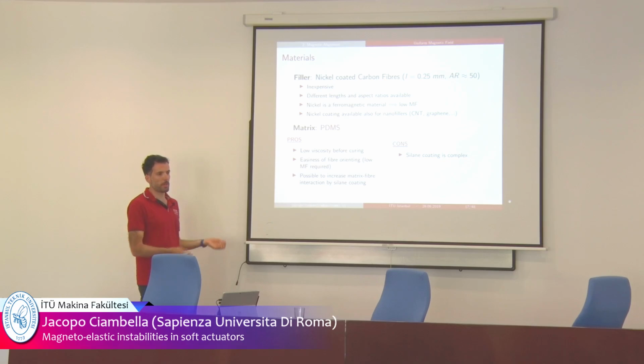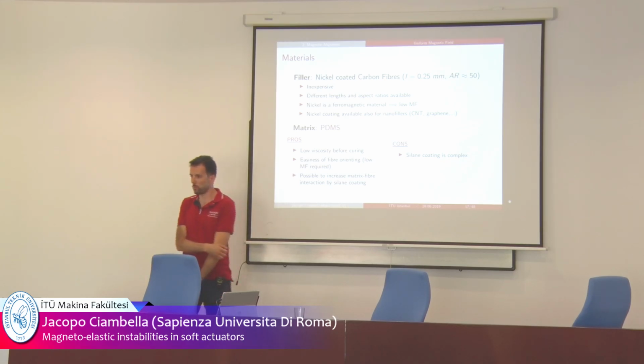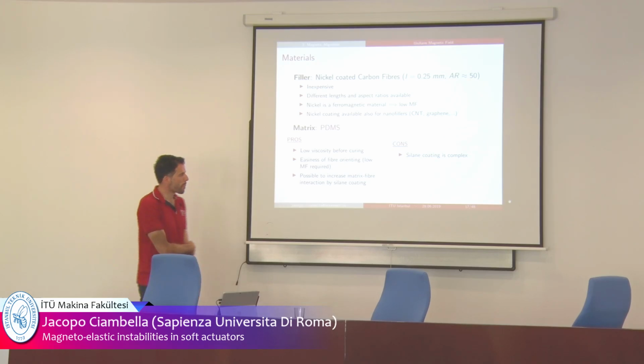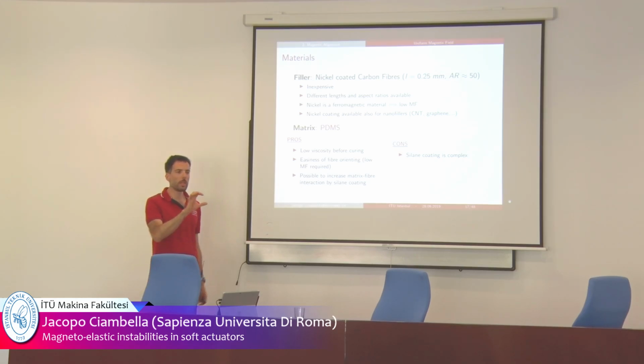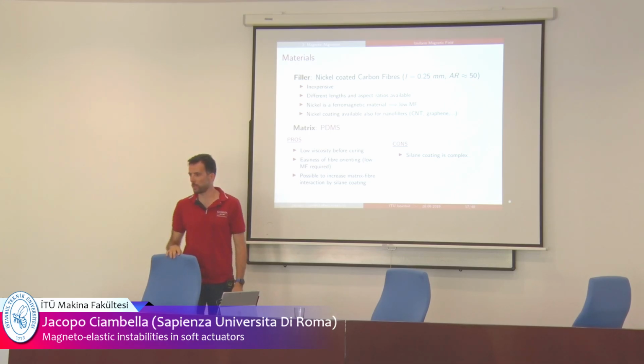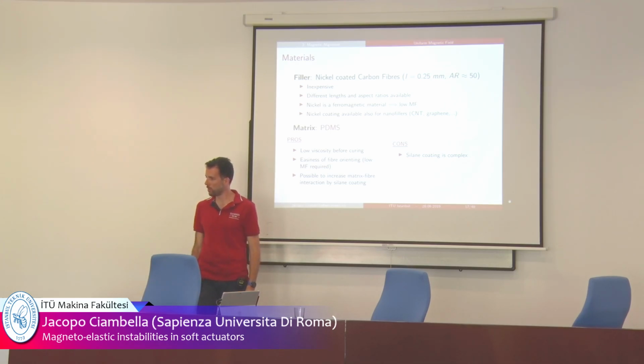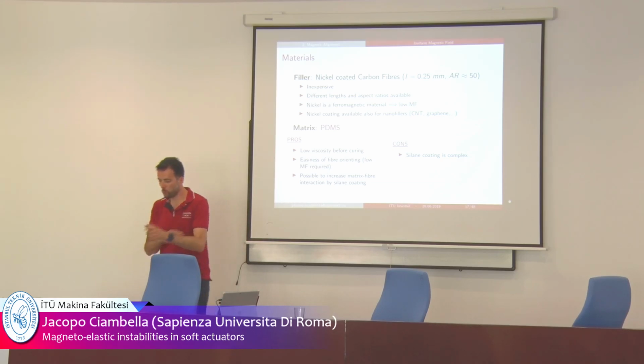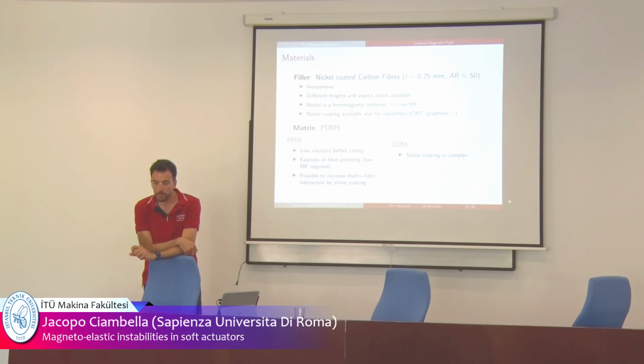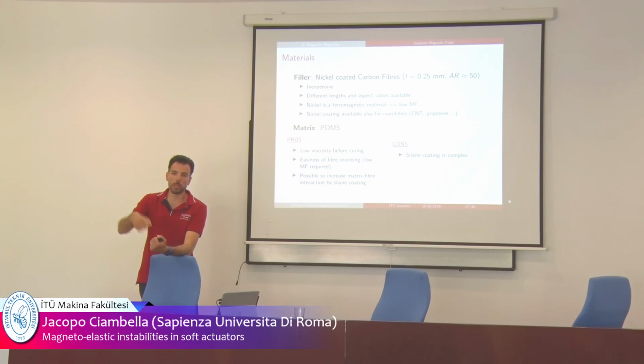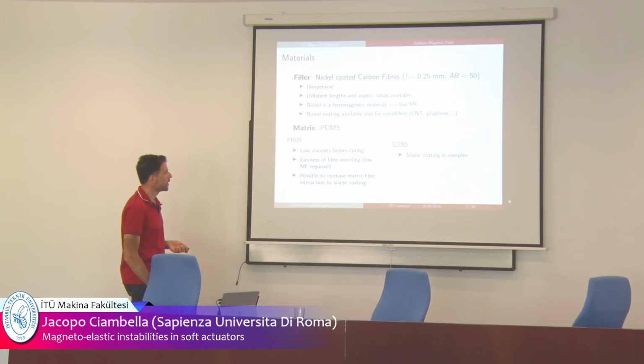PDMS is extremely easy to find, it's inexpensive, so it was the first elastomer we tested. The problem with PDMS, as I showed you, is that it is not easy to attach anything to PDMS, so it is very difficult to get a very good interaction between the matrix and the fiber. In fact, as we have seen in our experiment, sometimes the fibers were completely pulled out from the matrix, because the interaction was not very good, for some of them.